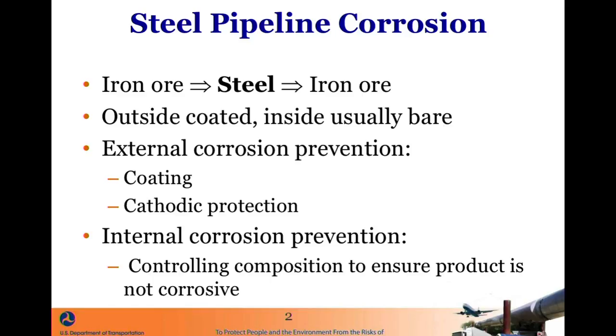And also we apply an electrical current because corrosion is an electrochemical process. We can drastically slow it down or prevent corrosion from occurring by applying electricity to the steel pipe. The main method to control corrosion on the inside is to control the composition of the natural gas to keep it dry, or if it's a liquid line, to keep water and other impurities out of that line. So in general, oil and gas is not corrosive to steel. It's just the impurities which are.